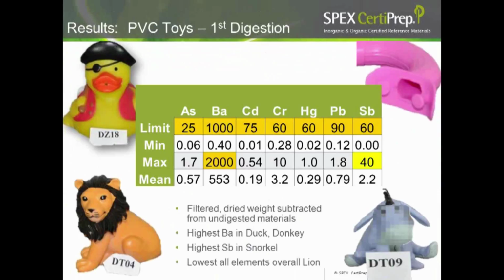It was a little anticlimactic, to be honest. We were expecting huge amounts of lead. We had read papers, we had done background research. We expected large amounts of lead in our samples. But what we found was that the lead limits were definitely way below what was allowed.